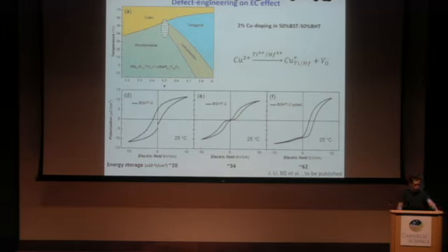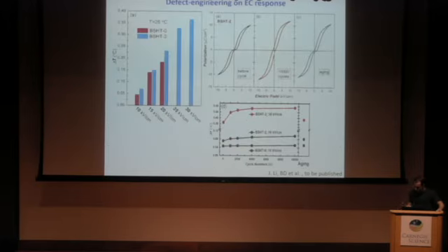Is this pinching changing by cycling? Yes, it's changing. It means that you will lose exactly here. You see, we have an increase of the remnant polarization in the system. But in the end, if we follow the delta T here, let's take for this one, it's for 10 kilovolt per centimeter, you see that we have not a big change, I would say, of the delta T by itself. I think it's nice that you have also slim polarization loop, so hysteresis losses will be relatively low. Yes, it's true.